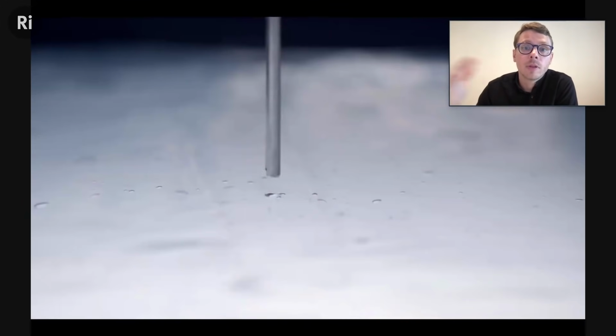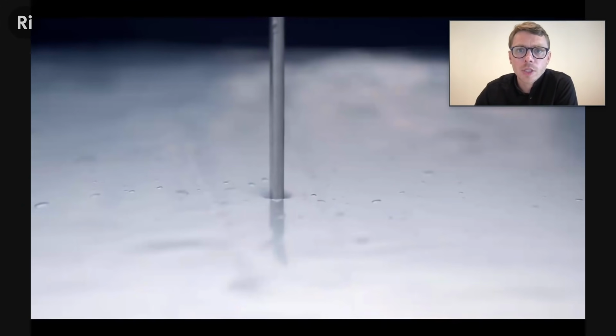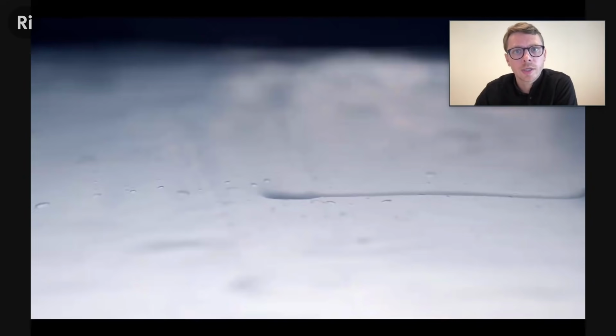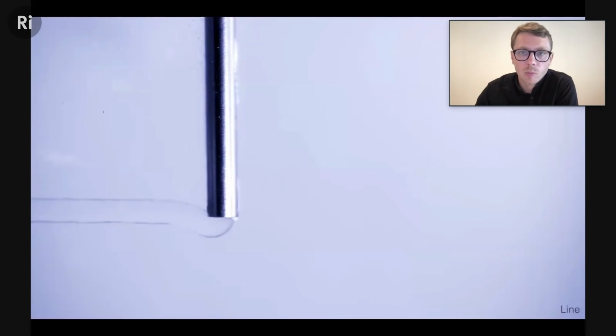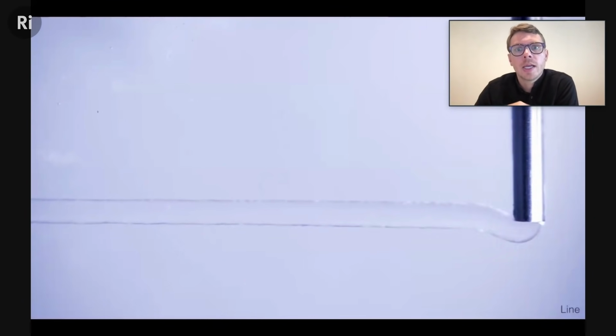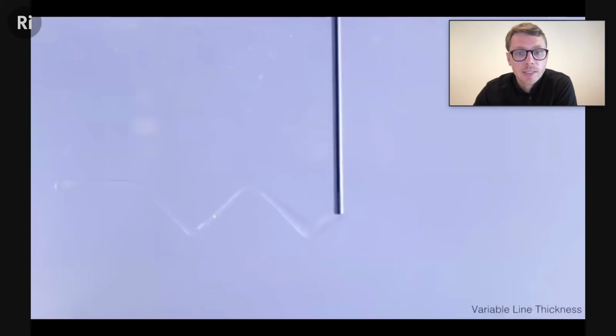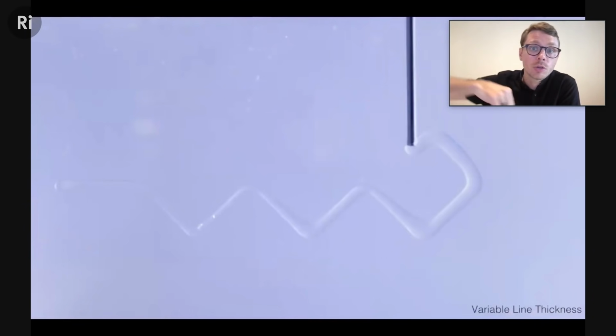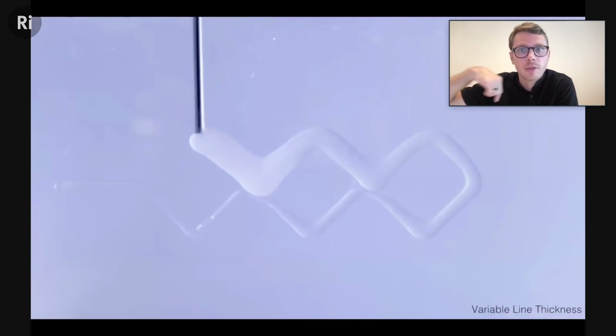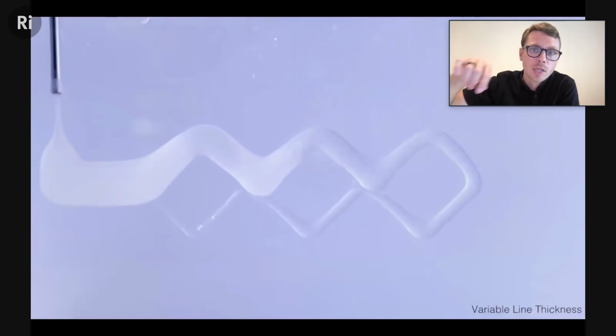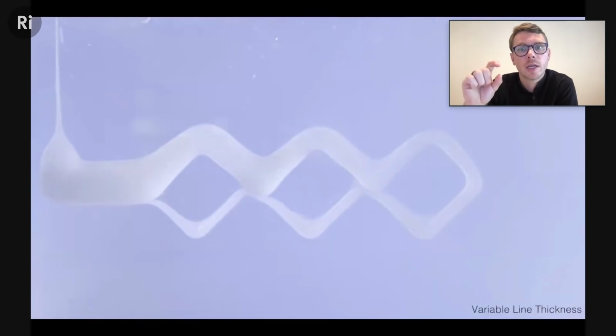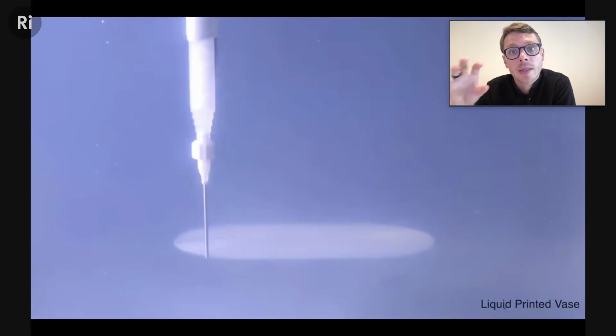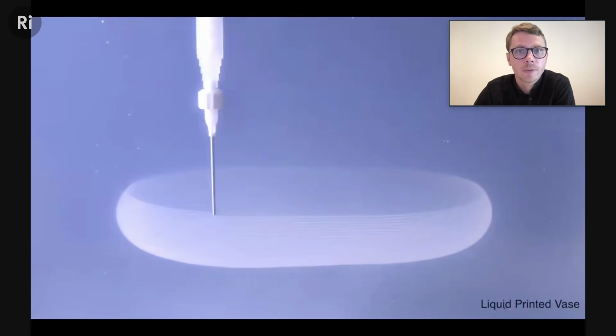So essentially, it's a large vat of gel. The gel is 99.9% water. It's safe. You can wash it down the drain. But the gel basically eliminates the effect of gravity. So you can print in three dimensions as if there's no gravity. It's like calligraphy. You're drawing in three dimensions. You can go faster or slower. You can change the extrusion rate to change the thickness. And then the material cures within the gel.